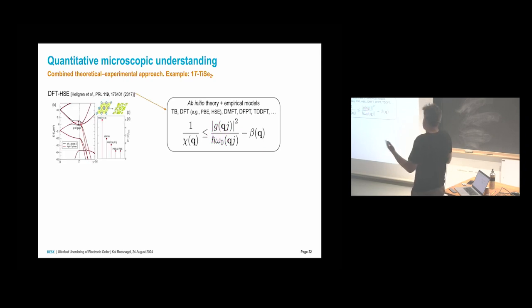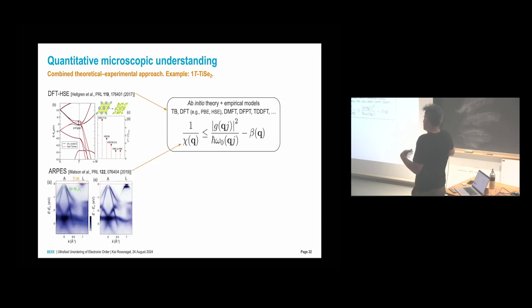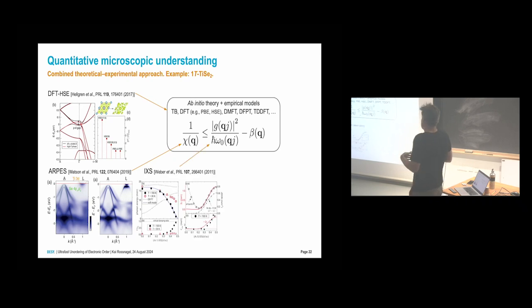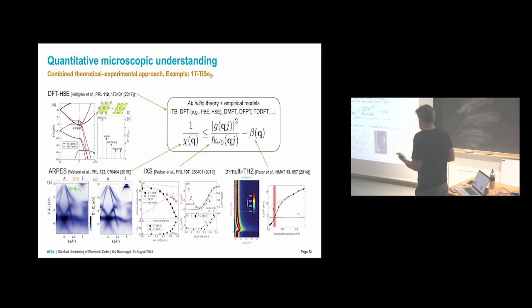For titanium diselenide, use the latest state-of-the-art density functional theory. ARPES, of course, gives you now very, very detailed images of band structures. Inelastic X-ray scattering or neutron scattering can give you all the information on the phonons. And other types of spectroscopies can really look into detail into these types of electronic interactions. And this would be really cool if an effort would be made to bring this all together and then try to quantitatively understand charge density wave formation, predict transition temperatures, and so forth.